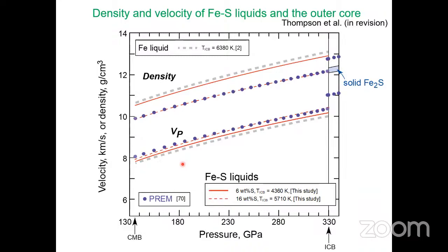Yeah, so according to the equilibrium experiments, like sulfur partitioning experiments between core metal and mantle silicate in the magma ocean, 2 weight% sulfur can be possible in the core. So that's the geochemistry argument. So 2 weight% sulfur is fine.